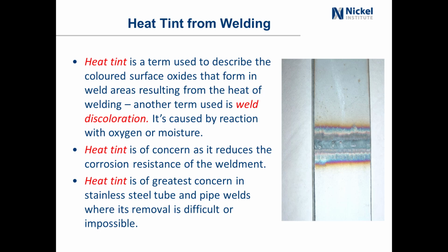Heat tint from welding. Heat tint is a term used to describe the colored surface oxides that form in weld areas resulting from the heat of welding. Another term sometimes used is just weld discoloration, and it's caused by a reaction with oxygen or moisture. Heat tint is a concern as it reduces the corrosion resistance of the weld. The weld becomes very susceptible to chloride stress corrosion cracking, partly because of the presence of these high temperature oxides that are formed during the welding process.